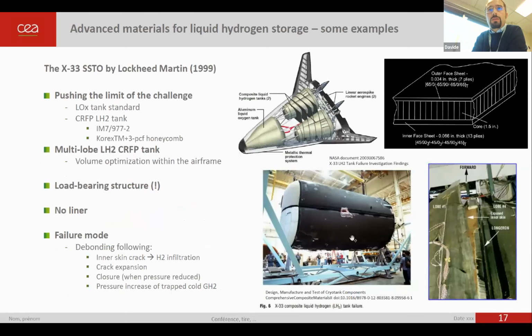So to complete very briefly, there are examples of cryogenic tanks manufactured and tested with advanced materials. The first example is from 1999, the beginning of 2000: the Lockheed Martin tanks. They went for CFRP liquid hydrogen tanks for this single-stage-to-orbit launcher. Alas, they maximized all the complexity. Basically, they went directly for a liquid hydrogen tank with a multi-lobe structure, with the load-bearing structure. The tank had to sustain all the launch load with a shape which is not cylindrical, with no liner and a simple CFRP. And of course, they had a huge delamination of the cores due to the cracking.